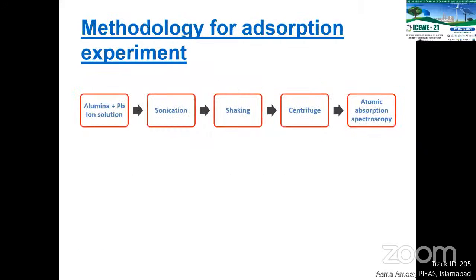Next was the methodology for the adsorption experiment. In the adsorption experiment, first of all, lead ion solution was prepared, and then lead ion solution was mixed with alumina, 0.01 gram of alumina, a very minute quantity. Then this mixture was sonicated for some time. Then it was shaken in an orbital shaker for about an hour, followed by centrifuge, and after centrifuge, atomic absorption spectroscopy was performed to find the remaining concentration of lead after the adsorption experiment.